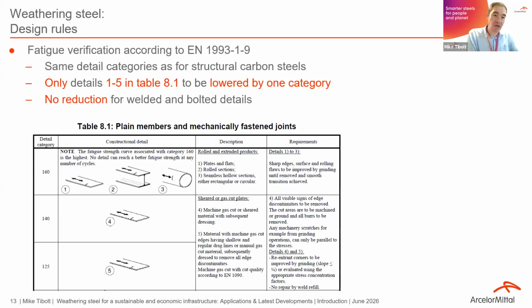For the fatigue verification, it is done according to Eurocode 3 Part 1-9, so there's nothing different compared to non-weathering structural steel. However, what we have to consider for the details that you could see in Table 8.1 of this, for the plain material, due to the roughness of this patina, we have to reduce the detail category by 1 for detail categories 1 to 5 in this table.